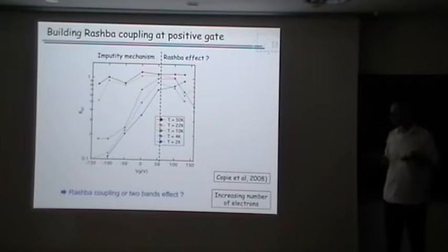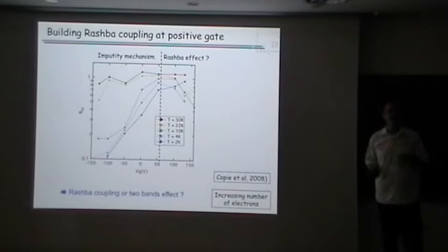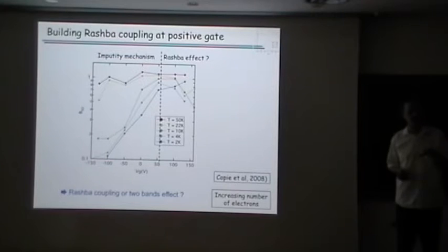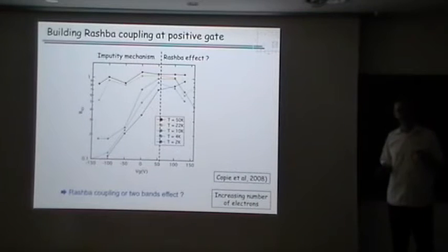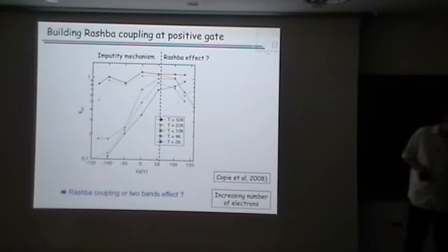Okay, so there is a rather strong issue here. The point is that we know that in this region we have two types of carriers. So we have to make a complete analysis again with two types of carriers in the localization regime and with the Rashba coupling, which we didn't do up to now, and we are still measuring the samples to be sure about this decrease here and how we can analyze the data, either on the basis of the Rashba coupling or just on the basis of a very crude two carriers model.